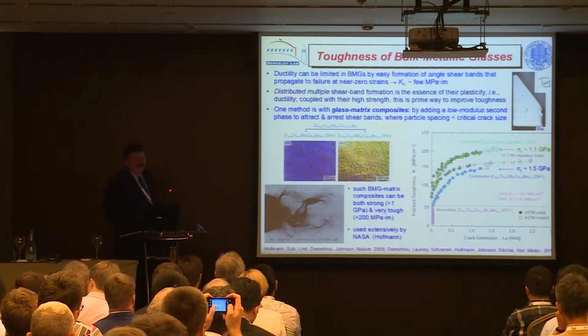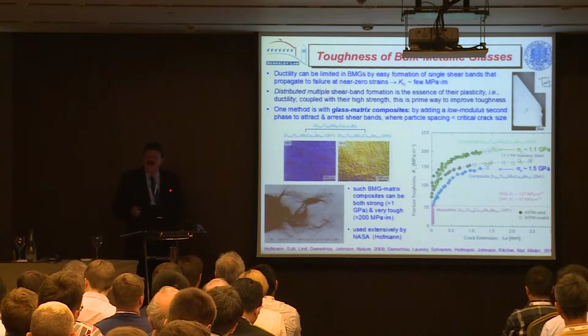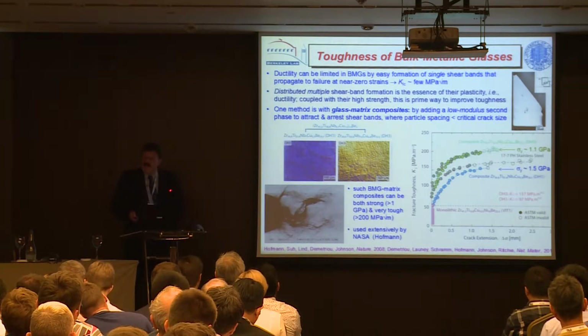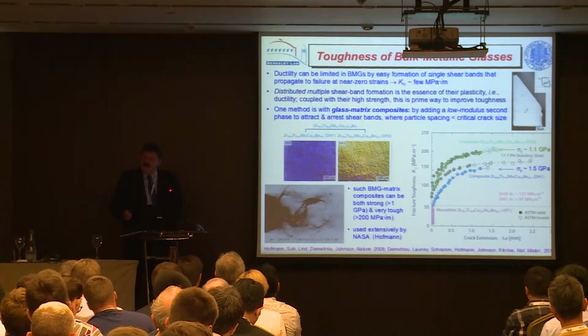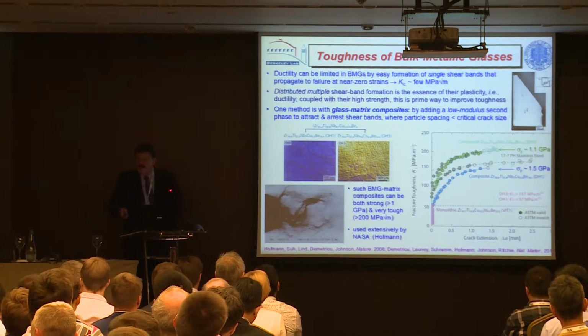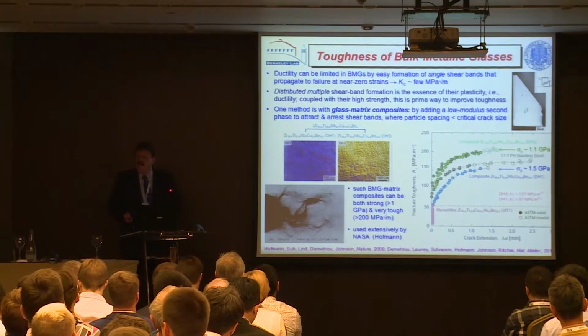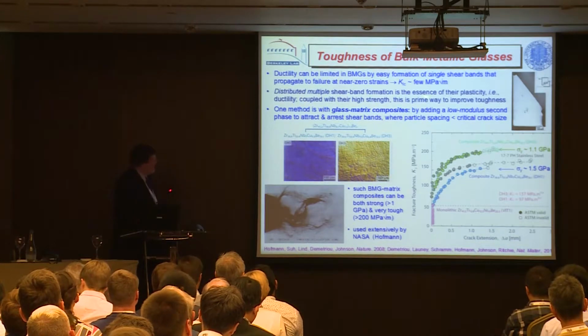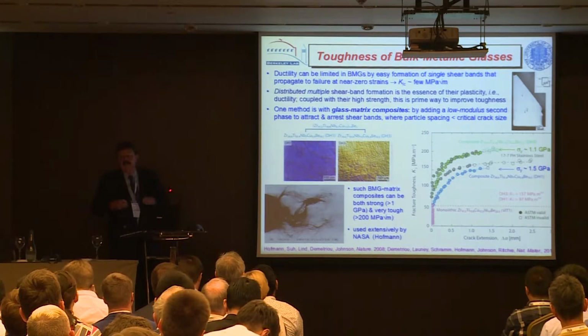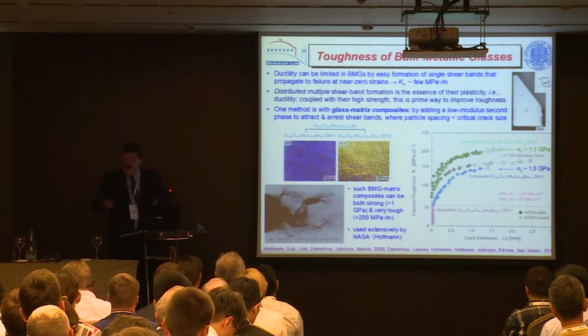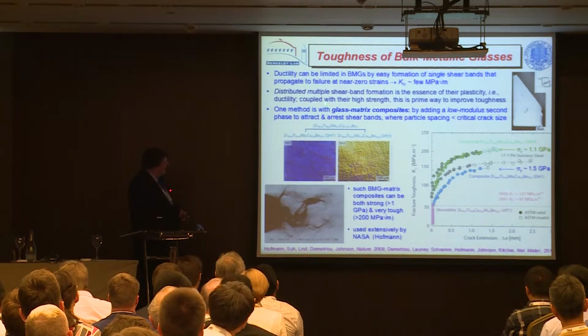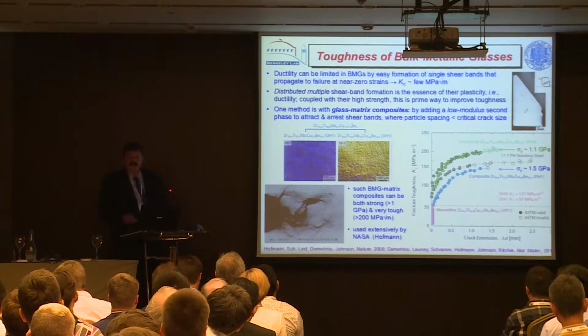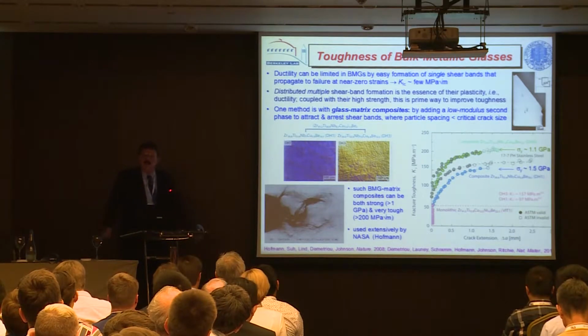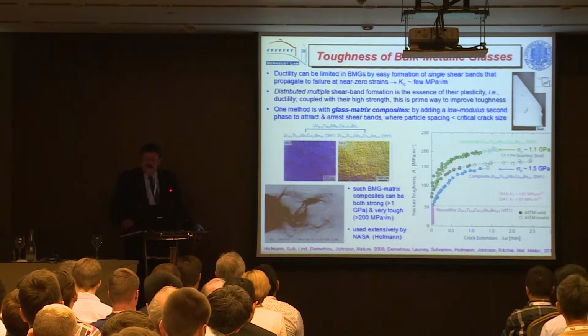Now, metallic glasses tend to have very high strengths. They're almost near theoretical strength in some cases. So if you can get plasticity, which generates ductility, not much, but enough, you can generate toughness. So the key to metallic glasses in getting a damage-tolerant material, you've already got the strength, you want to get plasticity, and in simple terms, that's promoting multiple shear band formation. Now, how do you do this?